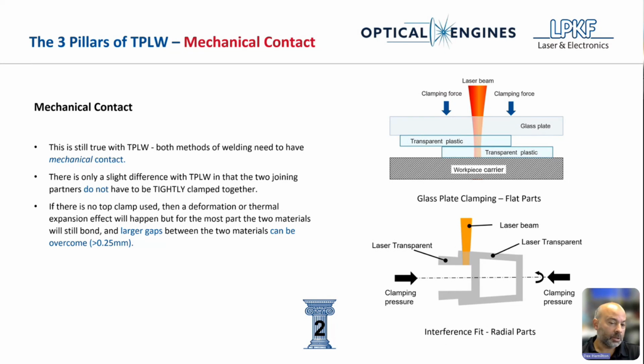But that doesn't limit us with TPLW to welding only flat parts. As you can see from the illustration below, this is just a cross section of a radial tube to fitting. Let's call it tube to fitting, for lack of better words. And we can weld those as they are interference fit. So pretty much any parts interference fit or clamping with glass plates is typical.